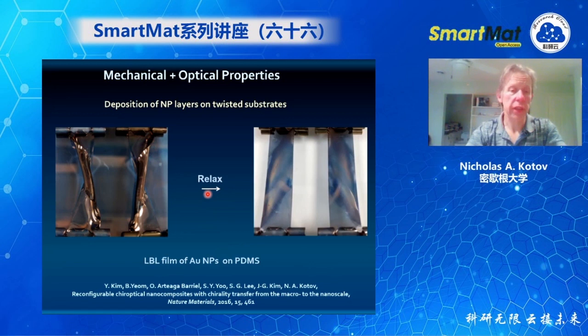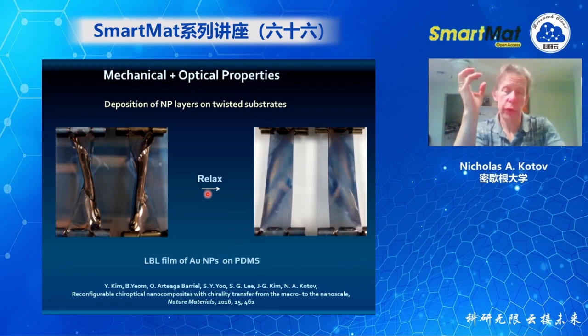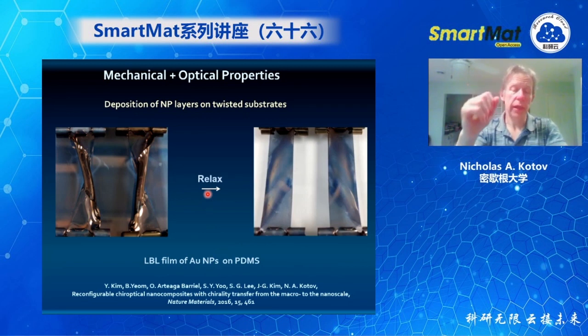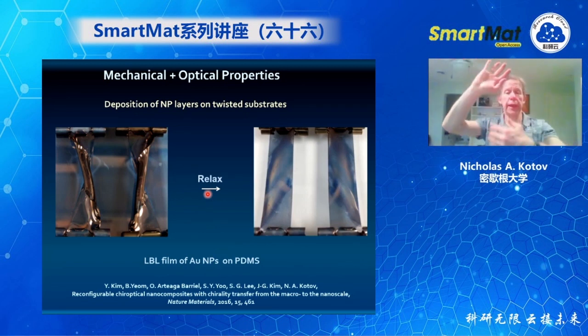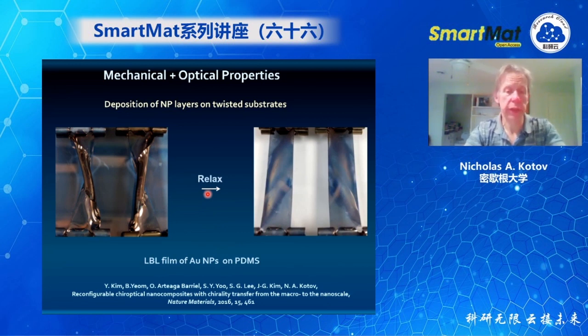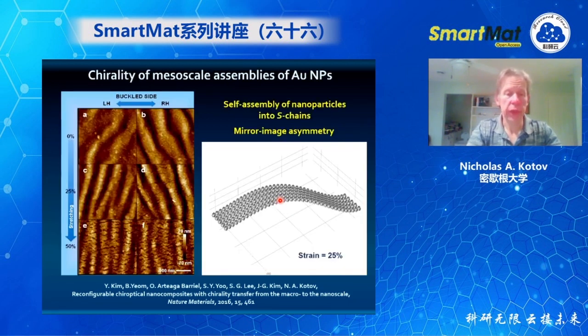So one advantage of this technique is that it can deposit particles at surfaces of any curvature. It could actually be deposited on nanoparticles. And after the deposition, we let the PDMS substrate relax and observed quite interesting opalescence. So immediately it means that in these surfaces, we have some periodic structure. We started looking at them with atomic force microscopy and saw actually two levels of organization.